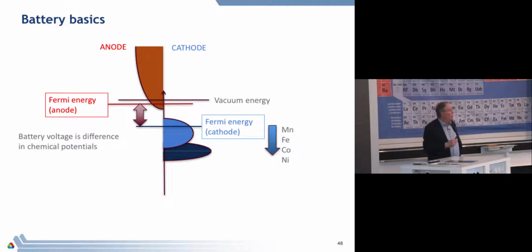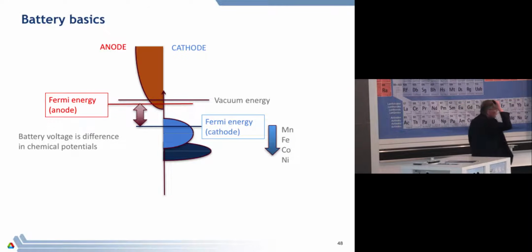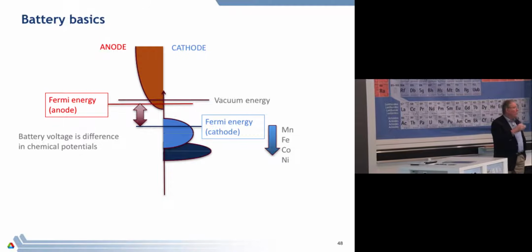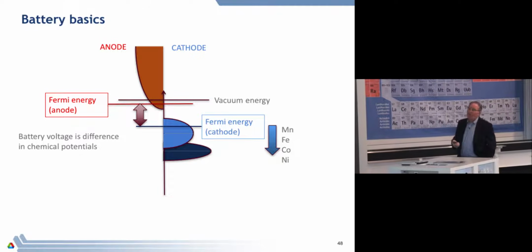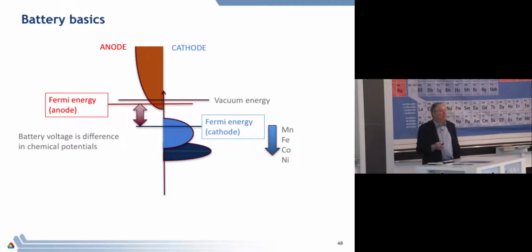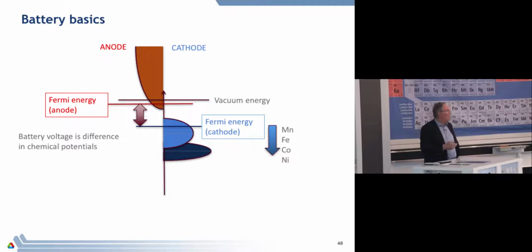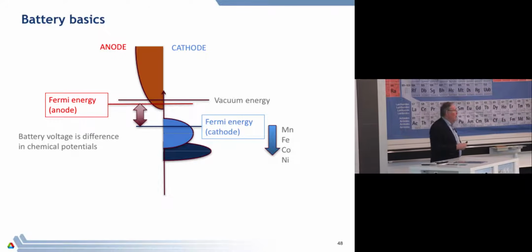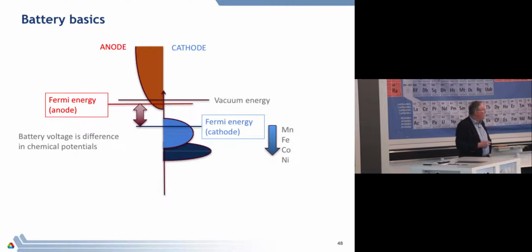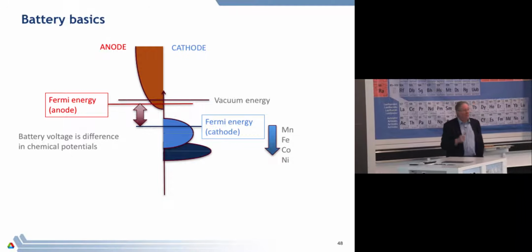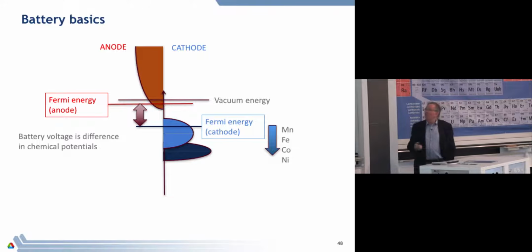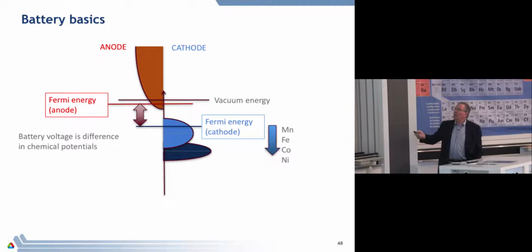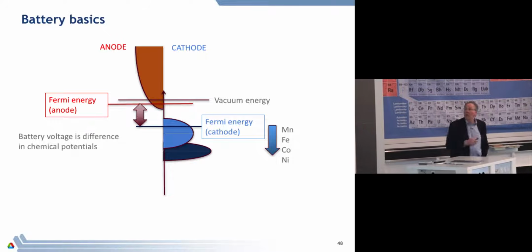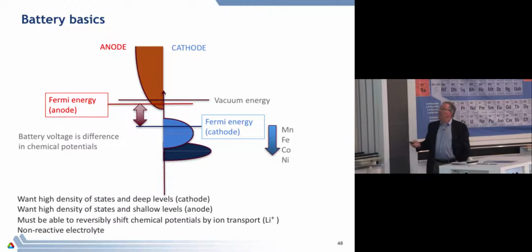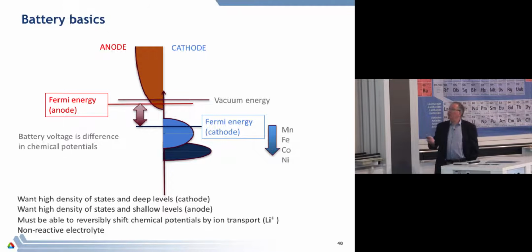and a big voltage. So if you know something then about transition metal oxides, so by the way, in the Sony battery, so-called, the anode is made of graphite, the cathode is made of lithium cobalt oxide, or something like this. So again, it's one of these transition metals, and the working ion that runs between these has to diffuse in there as lithium, shuttling around from one to the other. But if I want a good battery, so what do I need? I want high density of states and deep levels in the cathode.